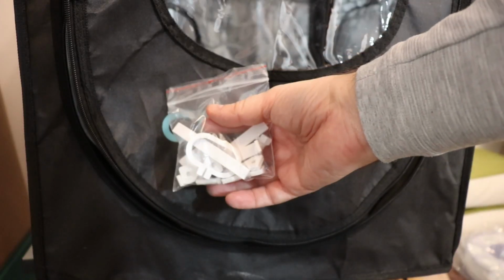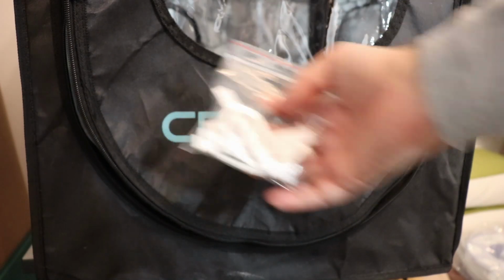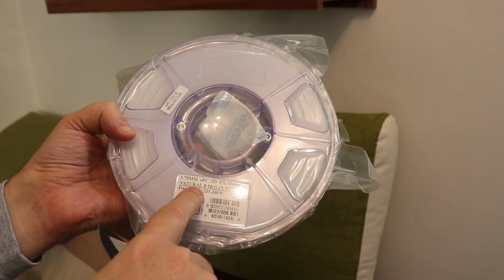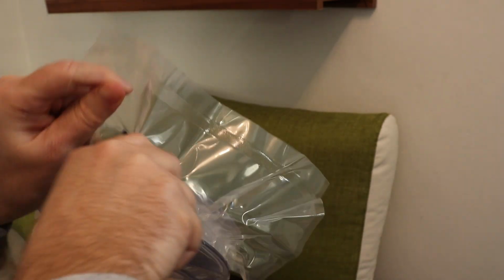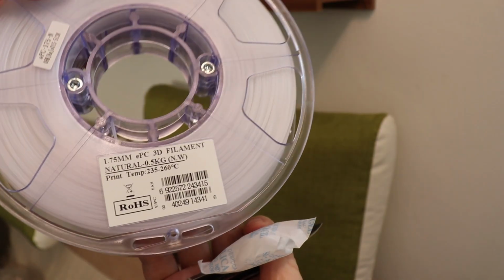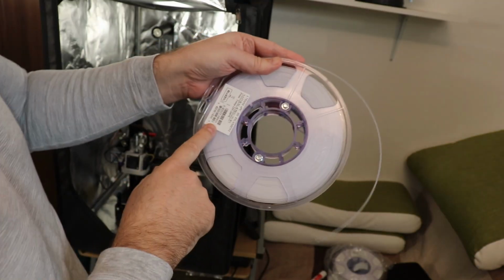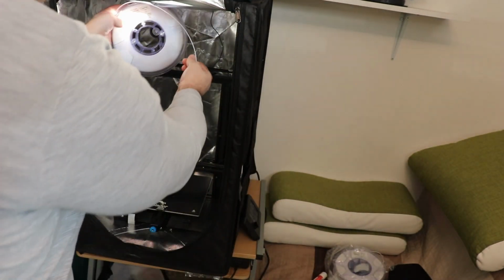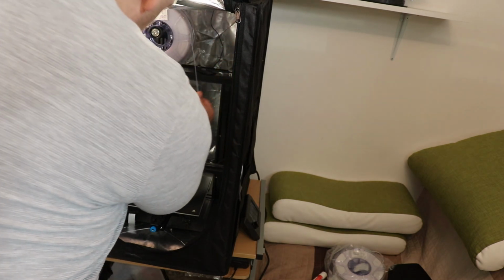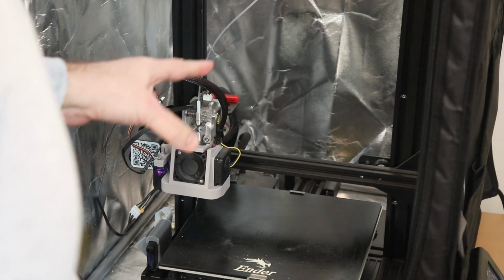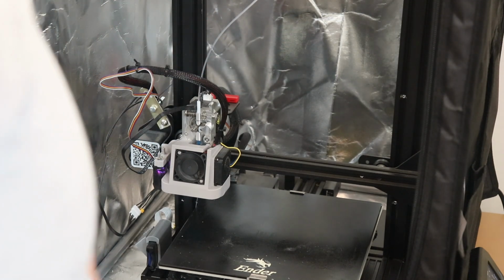All ABS parts are printed, ready for testing. And it's time to test polycarbonate. As you can see, this is a half kilogram spool. The nozzle is at 240 degrees Celsius and I can feel quite big resistance when I push with my hand. So yes, definitely this is the lowest temperature at which I will try to print this filament. But of course the temperature tower will always start from the highest temperature.